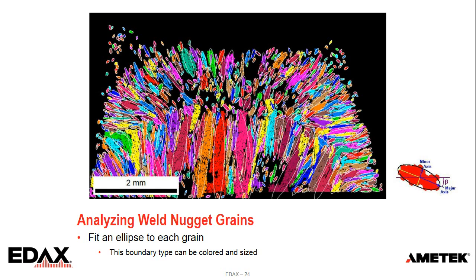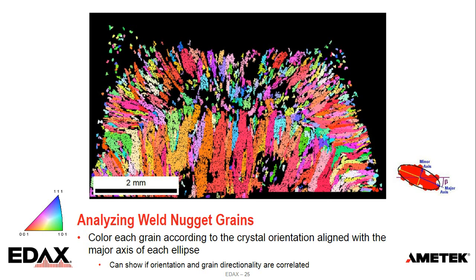So when we're looking at grains, we can get an idea of their shape and shape distribution. But from this, what I'm now doing is, we can see where the major axes are. I'm showing what crystal orientation is aligned with the major axis. And we can see that most of these, or at least a good number of these, are trending towards the red direction. That gives us an idea if some of that grows preferentially as the grains grow in that direction.